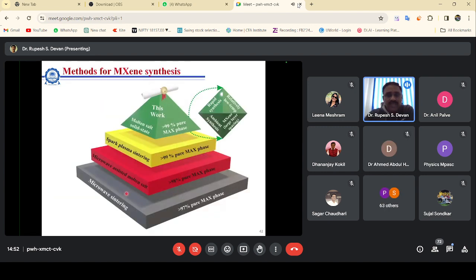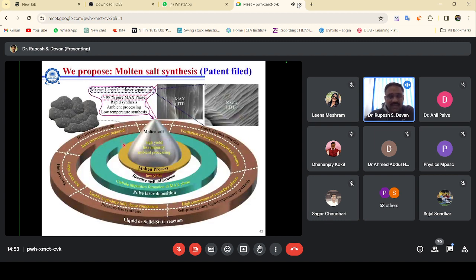Now, what is most important here is how these MXenes are being synthesized. Either microwave-assisted molten salt or plasma sintering is used, where 90% or 99% purity can be observed. But if you look at both these techniques, they require very high vacuum. So the cost of the MAX phase preparation goes higher. In India right now, it is available with 10 gram costing approximately 25 to 30,000. So the challenge was reducing the cost.